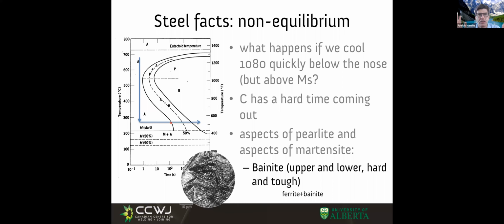Now, because I'm holding it, it's taking long to transform, because at low temperatures we have very slow diffusion. It takes very long to start transforming and very long to finish. Look, this is more than 100 seconds to start transforming. At this temperature, I could start transforming in 1 second. So depending on temperature, I can transform in 1 second or in about 2 minutes—same material. And to finish transforming, this would be about an hour, while this other one finished transforming in 10 seconds.